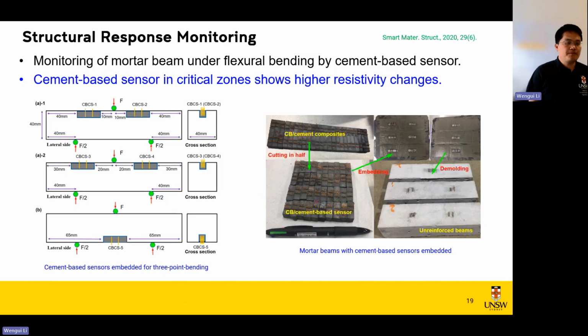Here we talk about the application of cement-based sensors for the structure response monitoring. And you can see the fracture bending test is conducted on a mortar beam with cement-based sensors embedded. And actually, the cement-based sensors are embedded in the critical zones of the beam in terms of compression and tension.